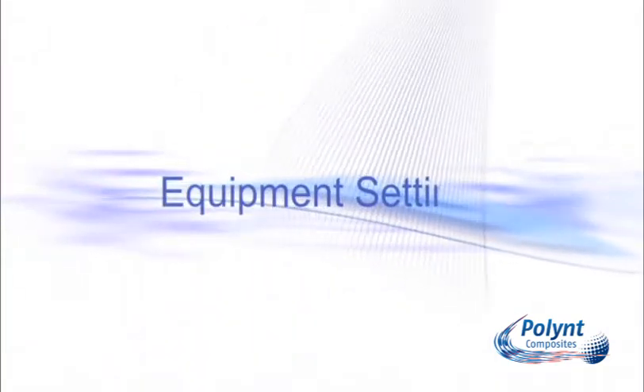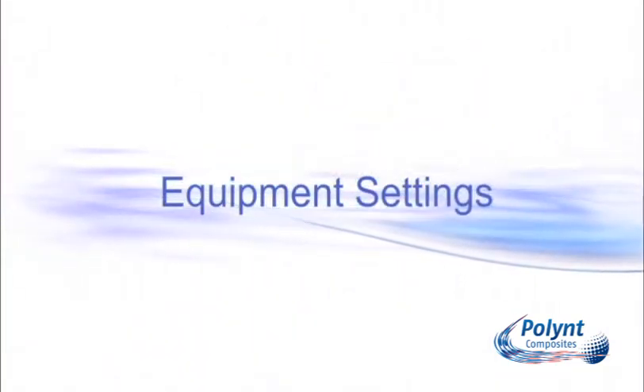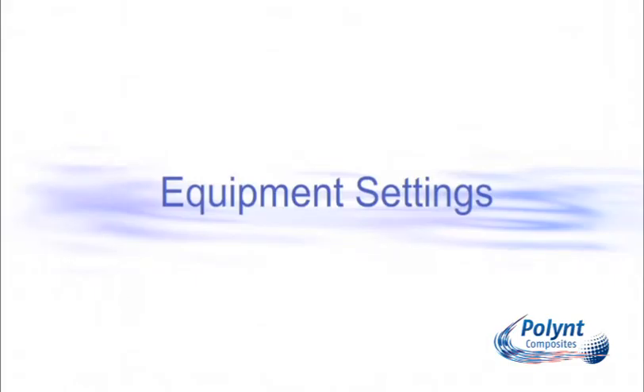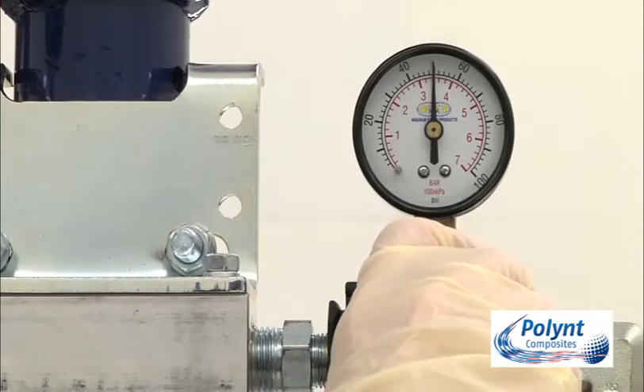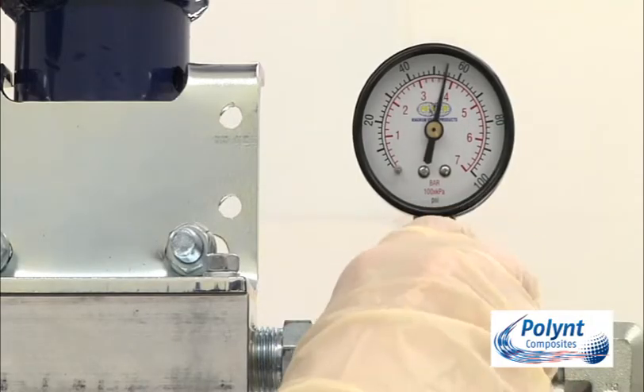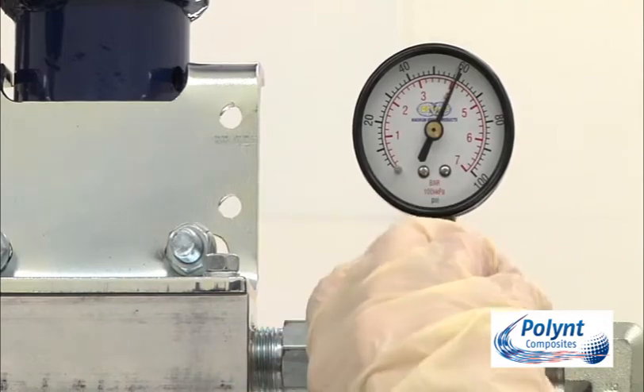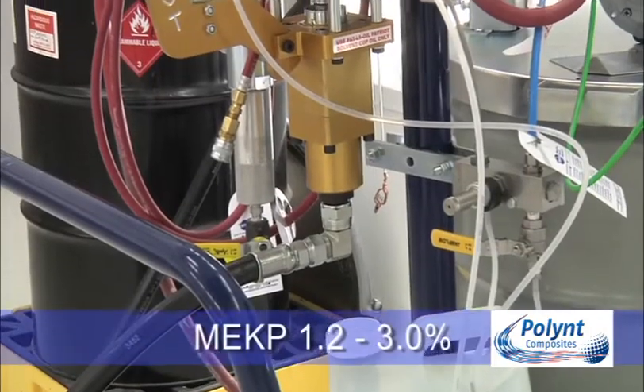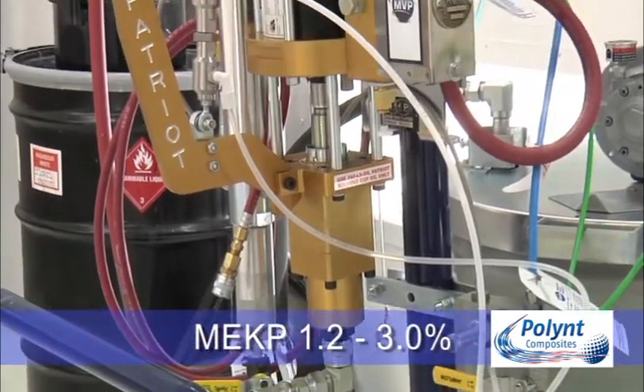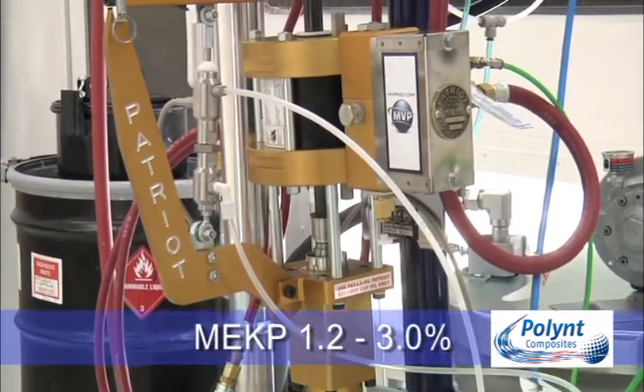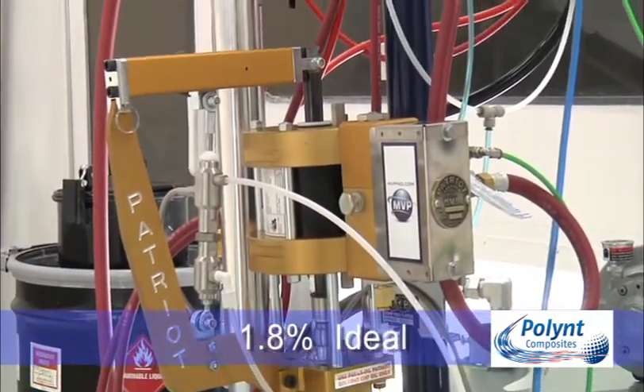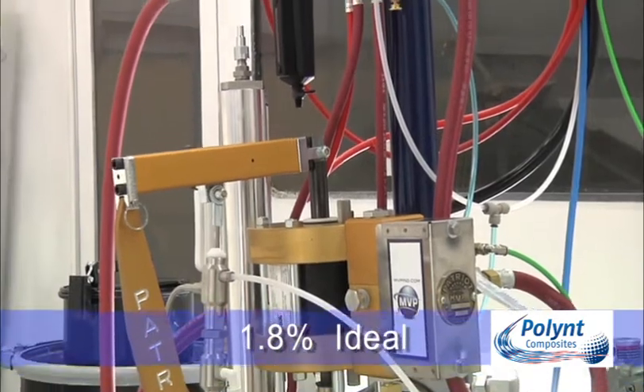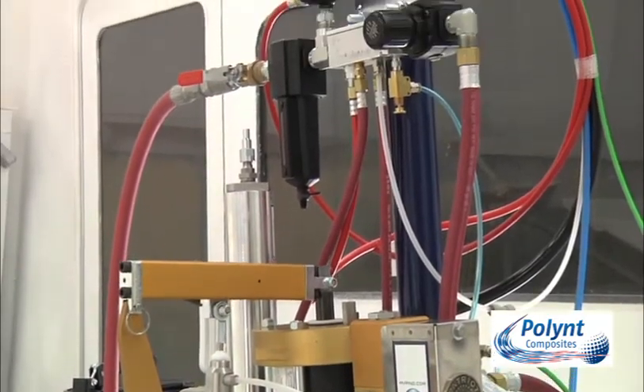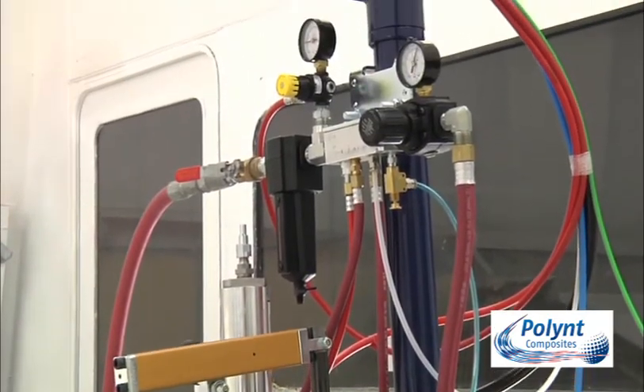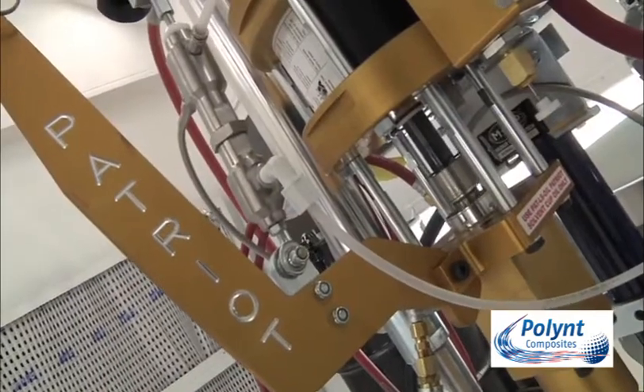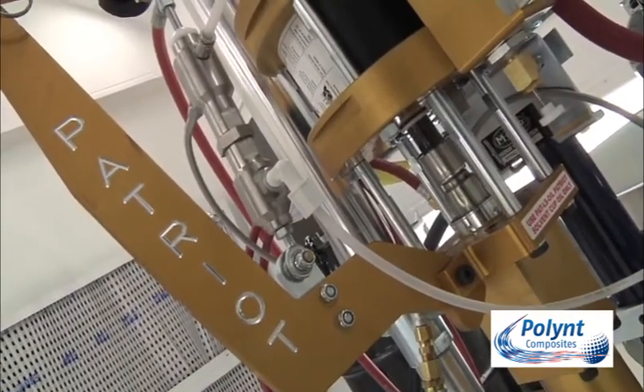Spray equipment needs to be prepared so that it delivers the right amount of material and catalyst. Material delivery is adjusted by changing the air pressure or changing the fluid tip orifice size. We recommend the use of Butanox LA type catalyst, and for most gel coats should be between 1.2 to 3%. 1.8% is ideal. Values are adjusted depending on the method of catalyzing gel coat. For this exercise, we set the catalyst levels at 1.8%.